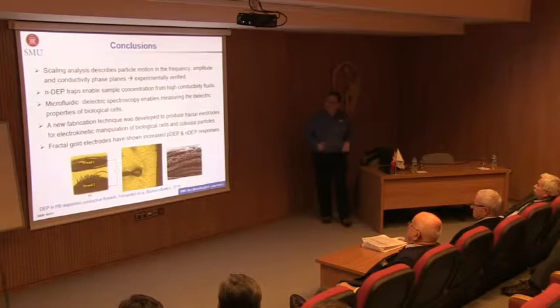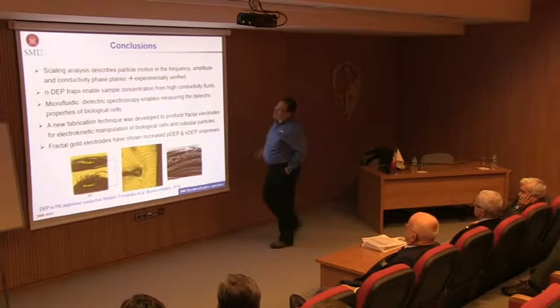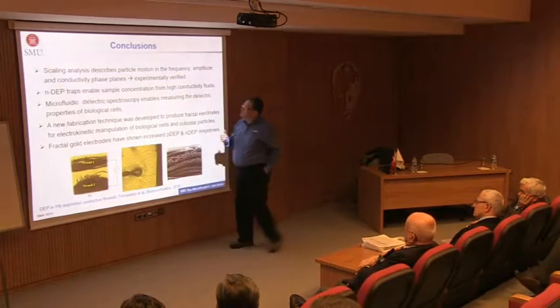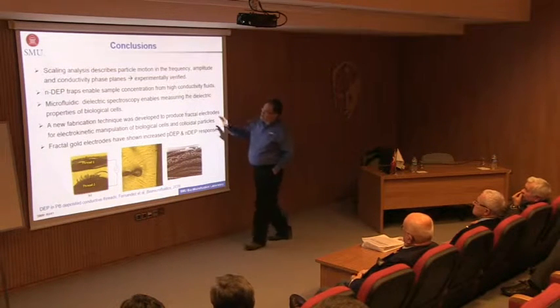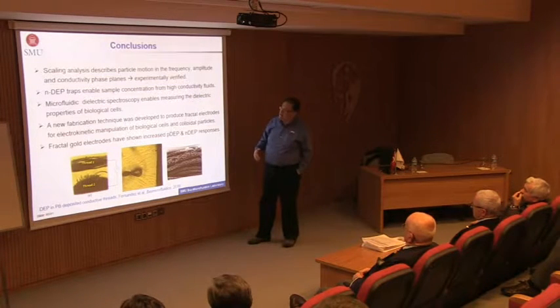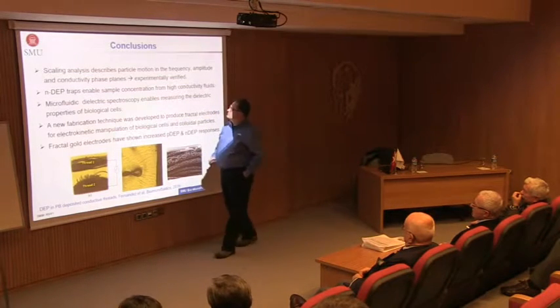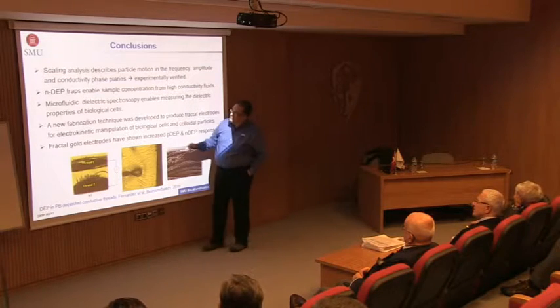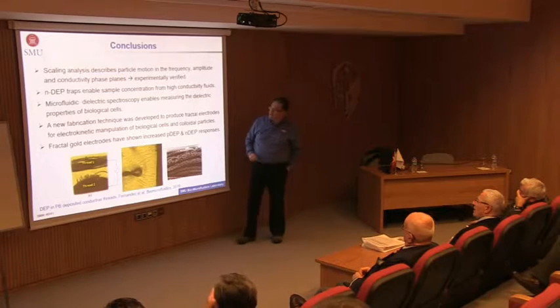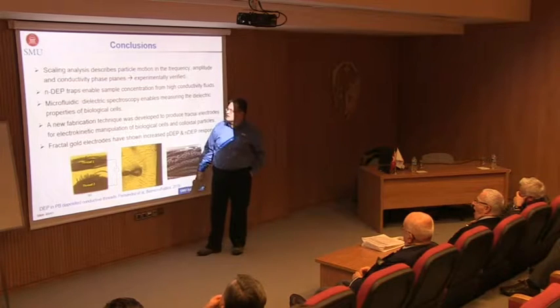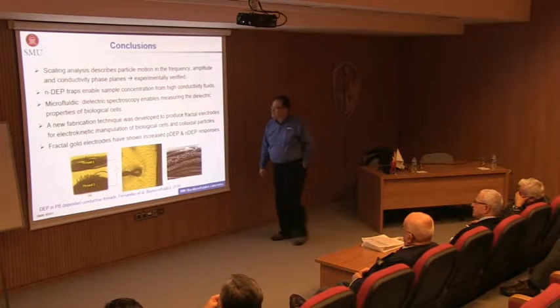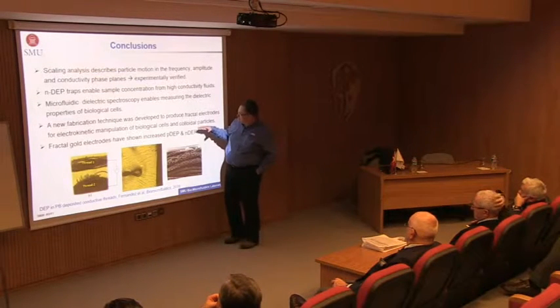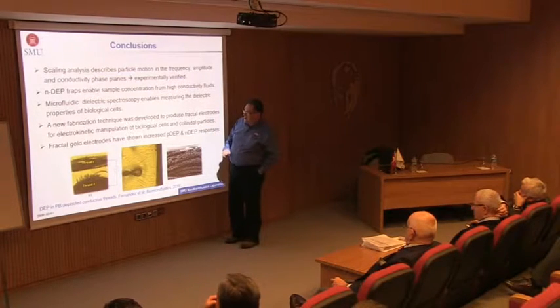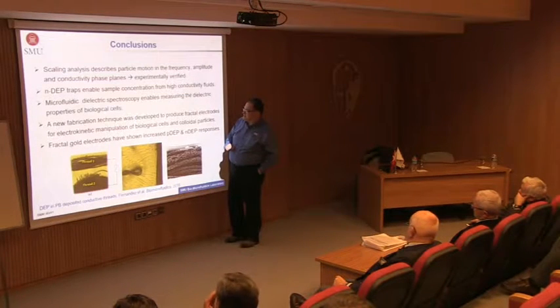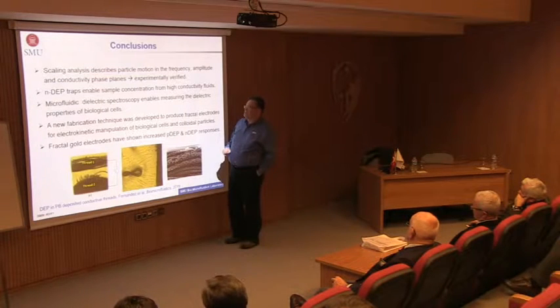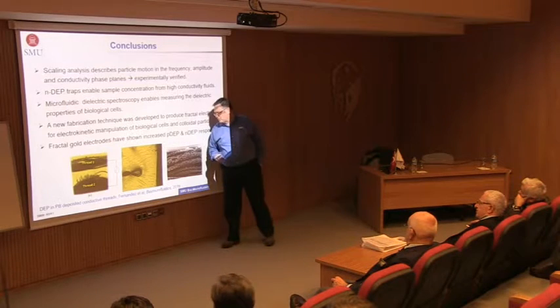So I would like to conclude by summarizing what we have done. I presented a scaling analysis which describes particle motion in the frequency and amplitude and conductivity phase planes, and which we experimentally verified. I have shown that we built negative DEP traps that enable sample concentration from high conductivity fluids, and the microfluidic dielectric spectroscopy we described enables measuring dielectric properties of biological cells, which can be used for characterization of the cells. And we developed a new fabrication technique by using this mask, and now we have fractal electrodes that actually do work well with colloidal particles and biological cells when it comes to both DEP as well as dielectric spectroscopy applications. And also, the last thing I have shown you was that fractal gold electrodes have increased DEP response both for positive and negative DEP.